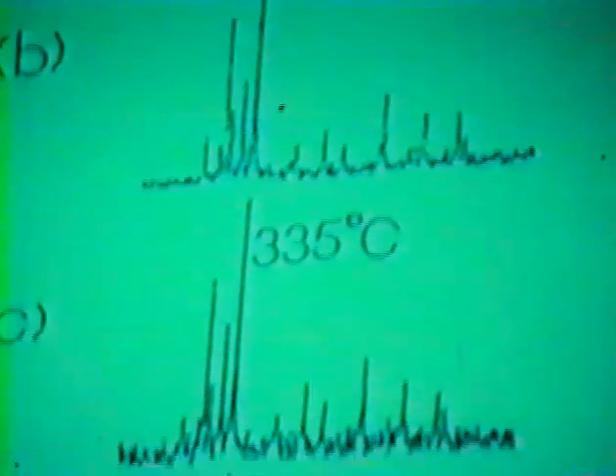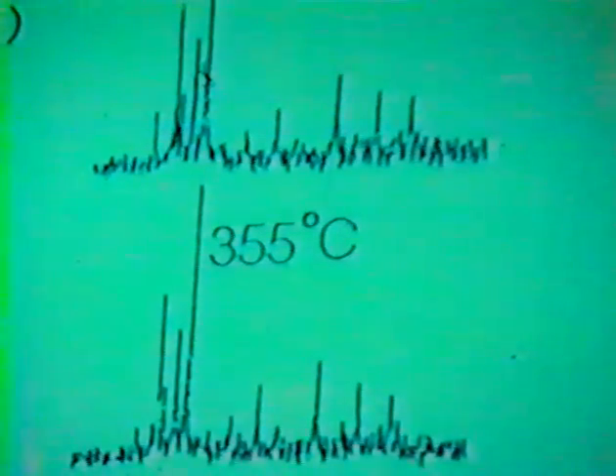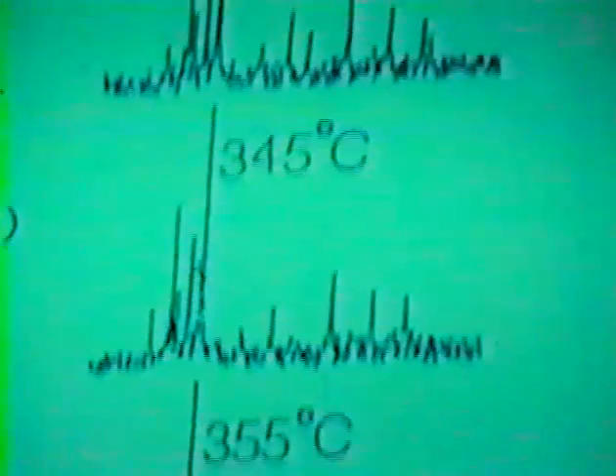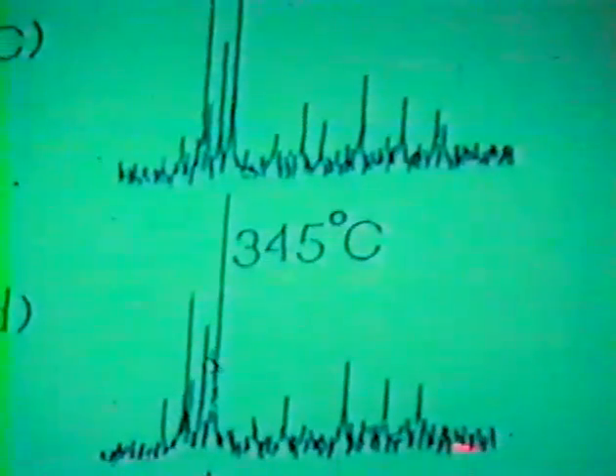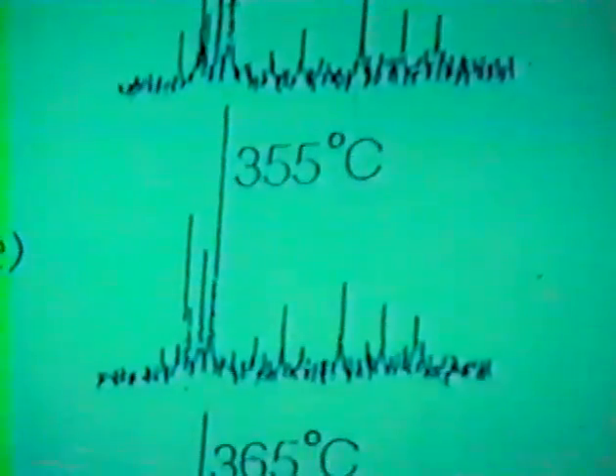Compared with the fresh catalyst, it is almost the same, and the intensity ratio for the carbon 111 to 200 is about 2 to 1, which is what we can expect. However, at much higher temperature, it gets down to between 1 to 2. And above 350 degrees, you can see it go back again, almost returning to 2 to 1. So the carbon is really changing.